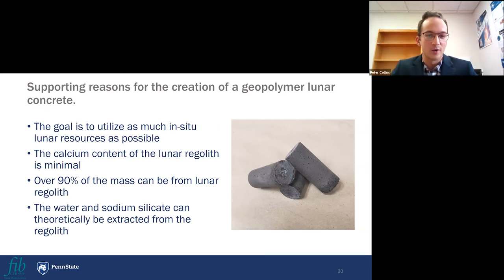So that's kind of out of the question right now. And that's why we're moving forward with a geopolymer concrete, given the composition of the lunar soil. And over 90% of the mass can be just of the lunar regolith itself. The remaining portion is your water and sodium silicate solution. The group that did the extra low solution ratios, I believe they had 95% of the mass was the lunar regolith. And so if you have lower solution ratios and added pressure, you can even get that number higher. But this really depends on the initial gradation of the material, as I have found out, and we'll get into that.